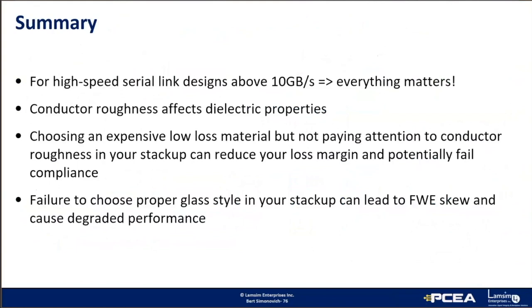So in summary then, for high-speed serial link designs above 10 gigabit per second, everything matters. And I've shown you how conductor roughness can affect your dielectric properties. So choosing expensive low loss material, but not paying attention to conductor roughness in your stack up, can reduce your loss margin and potentially fail compliance. And you're wasting a lot of money spending on a high performance dielectric and using rougher copper on it. Failure to choose proper glass styles in your stack-up can also lead to fiber weave effect skew and cause degraded performance.